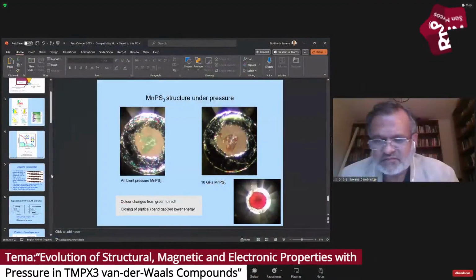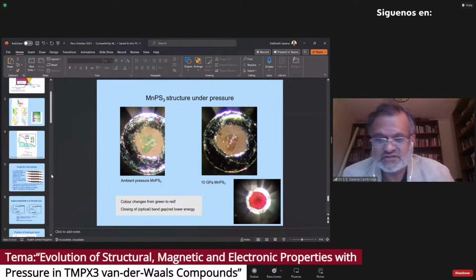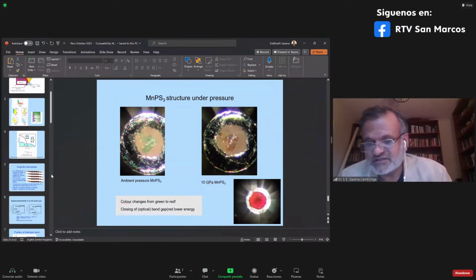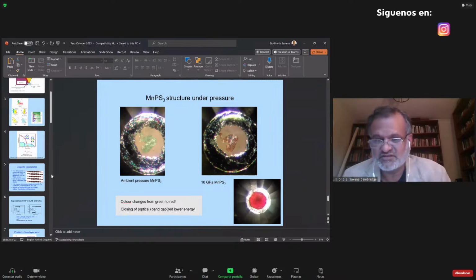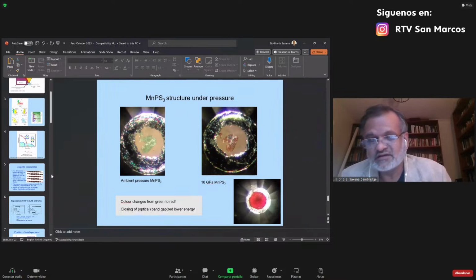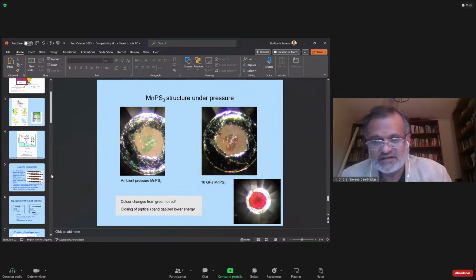I don't think, maybe I misspoke. I don't think we have shown or seen any evidence of a transition from a Mott insulator to a charge transfer insulator. It's just that when I used that word, it was that some of these materials start out as charge transfer insulators, and we have not picked them. We are just working with the ones which are Mott. So we're only seeing a Mott insulator to metal transition so far. And those, maybe we'll look at in future, but we haven't yet studied any. There was a speculation early on that the nickel version is a charge transfer insulator, but neither the DFT nor transport supports that. But then it would be starting with the charge transfer insulator. So I'm afraid I have to disappoint you. I don't have much to say about that.